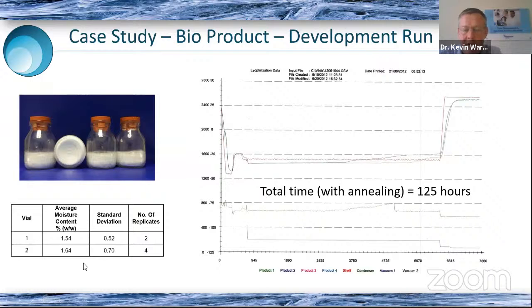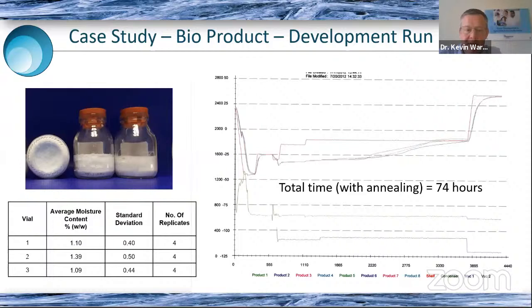What we then did is, knowing that we'd annealed the structure and opened up the ice structure and reduced the impedance to vapor flow, we then tried using a higher shelf temperature. So we had a couple of attempts here. As you can see, we changed the conditions during the cycle according to the data that we were getting from the freeze dryer, particularly in terms of the product temperature. So still here now, it's still below about -35. Well, we'd established that we could actually have it at a higher temperature than that, but we tried to do things incrementally and step by step.